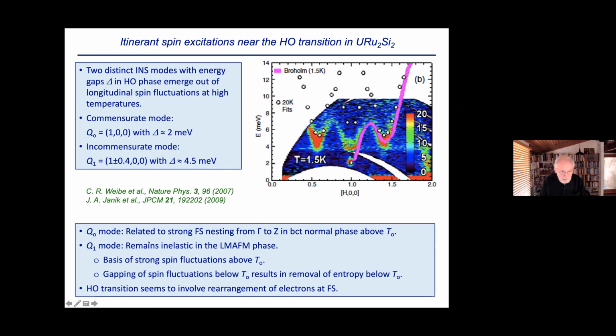And then the Q1 mode remains inelastic in the large moment antiferromagnetic phase. And it's the basis of strong spin fluctuations above T0, and then the gapping of spin fluctuations occurs below T0, which according to Wiebe in this original work results in the removal of entropy below T0. And so they conclude that the hidden order transition seems to involve some rearrangement of the electrons at the Fermi surface. And although I won't really get to that part, a recent